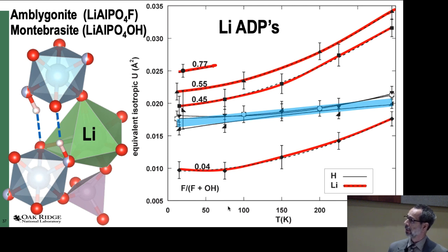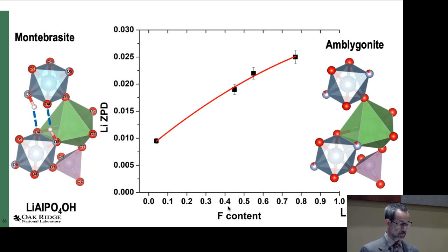Here shown in the red highlighted curves are the atomic displacement parameters as a function of temperature, where with increasing fluorine content from 0.04 to 0.77, you can see the 0 point displacement shifts up. So even though these have similar slopes, what we're showing here is that the lithium 0 point displacement increases with fluorine content.